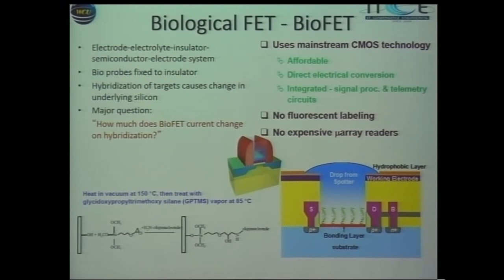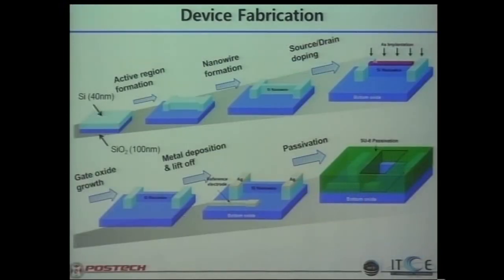If you have a probe that sticks everywhere and a poor surface in the neighboring area, you will get binding from all over that contributes to the current and confuses the signal. No matter what you use for diagnostics, it is your responsibility to make sure that the surrounding surfaces prevent non-specific binding. What makes this device unique over the gate area is a small reservoir where you put your sample. We use a silicon nanowire for the material — not a bottom-up nanowire grown using catalyst, but a top-down processed nanowire, which is much easier since the process is well known.